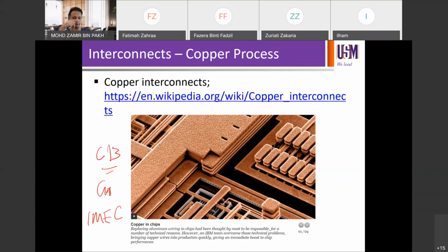development lots, development wafers. The challenging thing about copper is you cannot contaminate your silicon with copper. We learned last time in 386 that copper, C13 is copper based. Copper is a lifetime killer in the silicon. We learned this when we learned about defects, recombination, lifetime killer in silicon.